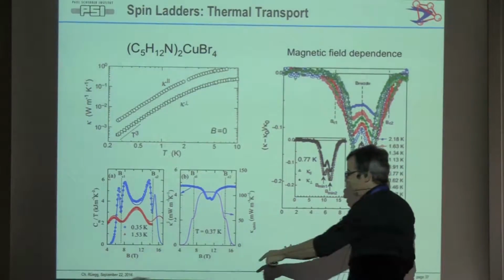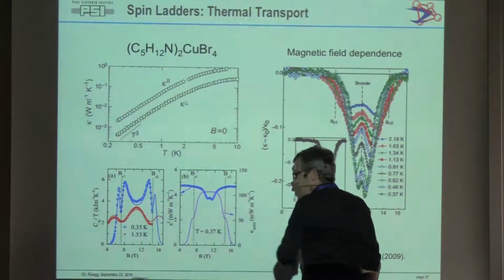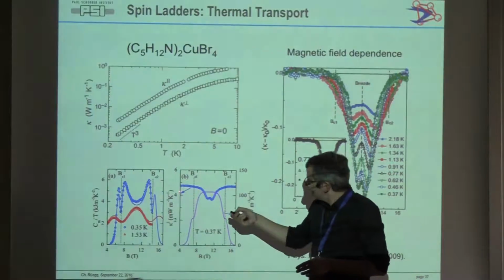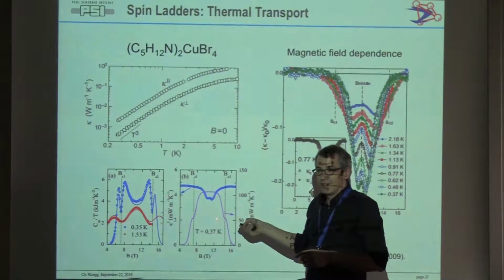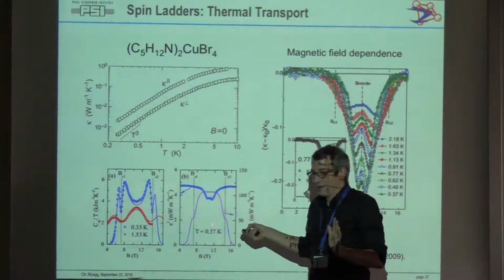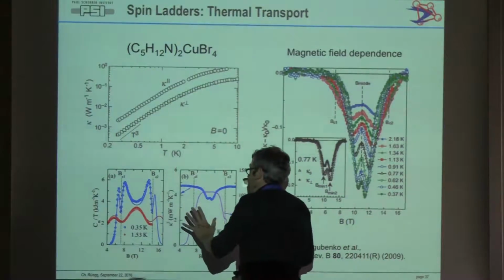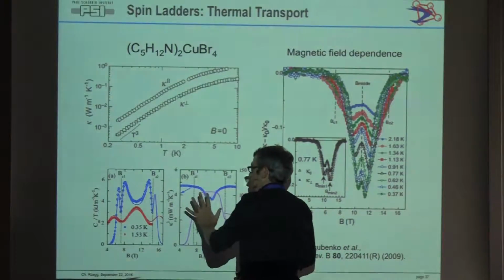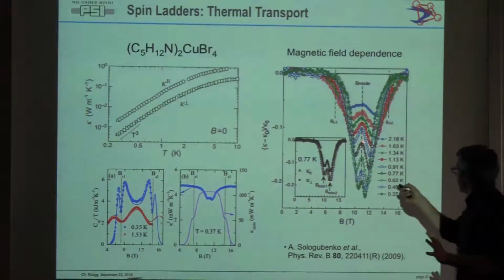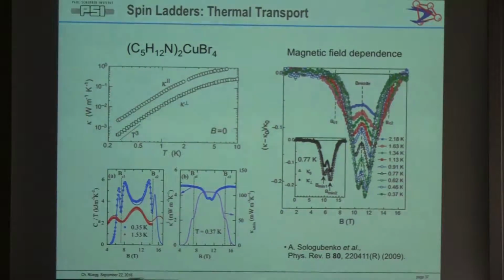We did the same calculation. You can see this solid line here, beautiful. And then we look at the measurement, and it does exactly the opposite, and with roughly a factor of 5 or so difference. So at that stage, we didn't know a good explanation for this. And here you see also temperature dependence. We were actually quite low in temperature. You see also some significant features. So for all the theorists in the audience, I think this would be a good challenge.